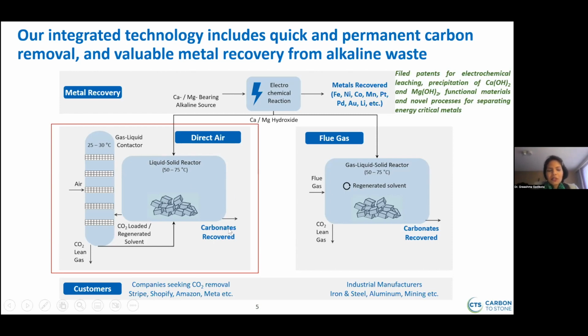So here for this audience, we're focused on direct air capture. And what is to note is that in some scenarios, it doesn't make sense to harness the alkaline resource for metal recovery. This is particularly in residues that really don't have very high quantities of energy critical metals, in which case we just bypass this entire step at the top and go straight to direct air capture and mineralization. So most of the economics and the life cycle assessment that I'm going to show you later on is for a material that can be directly mineralized and from which we don't have a need to recover metals, if I may. Having said that, we have patents for how we could recover a wide range of different metals, including iron, nickel, cobalt, manganese, platinum, palladium. We're also able to recover rare earth elements and lithium as well. That's a whole other topic in and of itself. So I just want to stay focused on our carbon removal strategy here.